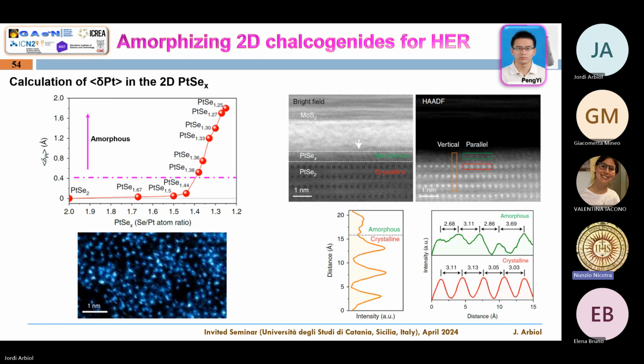And what you can see, this is a cross section. In this case, this is not the atomic layer. What we did is grow a thicker layer because otherwise we cannot prepare it by FIB. But we were attacking it in order to see how the top layer was reacting to the plasma. And you can see that in the layers inside, the distance is constant, but on the top layer, this is the random distribution. Every single atom is in a different position.